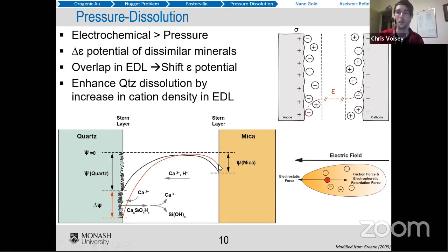So he brought quartz together, he brought mica together. He had a solution in between them, which had calcium and hydrogen in it. And what he found was that the calcium would go to the quartz surface. It would make this metastable molecule here, calcium silica hydroxide, and that would be stable until it moved away and it would break into calcium and silica hydroxide again. So under this electric field, going from basically a positive surface to a negative surface, you had positive cations go to the negative surface, scavenge bits of it, and then float away. And that's what was causing pressure dissolution.